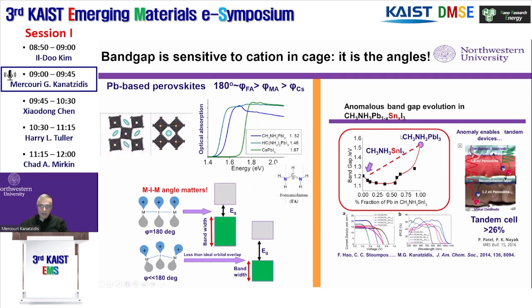Another thing is this anomalous band gap behavior. If you make a solid solution between the lead and the tin, you don't get the Vegard's law. In a classical semiconductor, let's say if you make a solid solution between silicon and germanium, the intermediate compositions will have intermediate band gaps following more or less a linear behavior. The same if you mix cadmium selenide and cadmium telluride. But here we have an anomalous trend where the middle compositions have even lower band gap than the lowest band gap member. So the lowest is 1.2 eV, but you can get down to almost 1.1 in the middle.